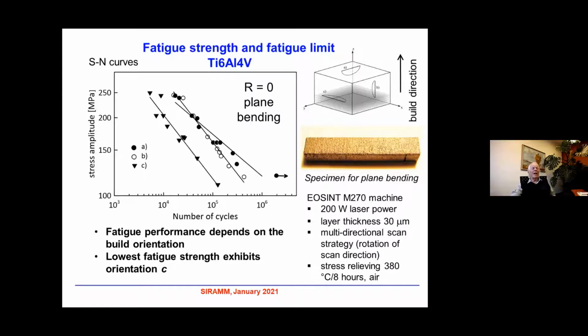So we prepared 3 types of specimens with 3 orientations. It is shown here. The first case, which is denoted as A, means that the specimen is loaded in such a way that the crack initiates on this surface and then propagates across the layers in this way. So it propagates opposite to the build direction. Case B, it is this case, means that the crack initiates on this surface and propagates again across the layers. However, the crack plane is parallel to the build direction. And the third case is when the crack starts on this plane and is propagating along the layers. It is case C.